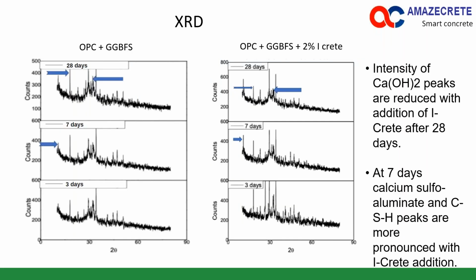So XRD examination of concrete with and without iCrete shows the intensity of calcium hydroxide peaks is reduced in 28 days. You can see the calcium hydroxide peaks are reduced from here to here, and then calcium sulfoaluminate peaks are more pronounced. You can see calcium silicate hydrate peaks are more pronounced actually. So this shows that iCrete works and changes the microstructure of concrete, imparting better permeability and strength.